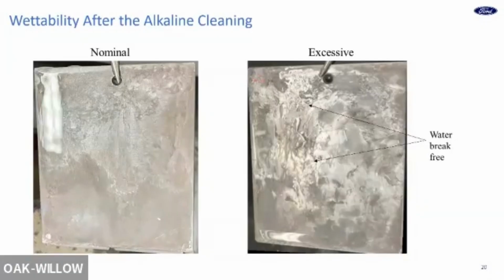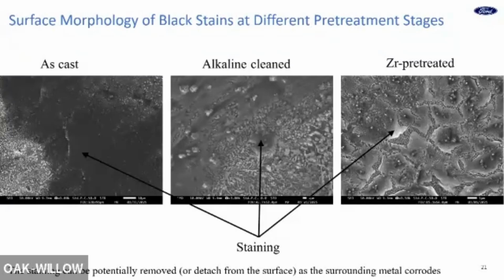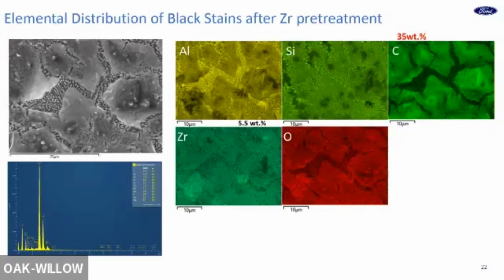So to better understand what really happened in this water-break-free area, we look at the surface morphology change at different stages. At the cast condition, you can see a lot of black staining. It's mainly rich in carbon. And then after cleaning, you see some lubricant is removed. And also, you see a lot of etching under this staining, meaning some etching really goes under the lubricant residue and still etches the metal substrate. And after zirconium pretreatment, there's not much obvious change. This EDS further shows the presence of lubricant residues can be very high in some local areas. But interestingly, zirconium still can deposit on this carbon, maybe because the carbon is also a strong cathode.